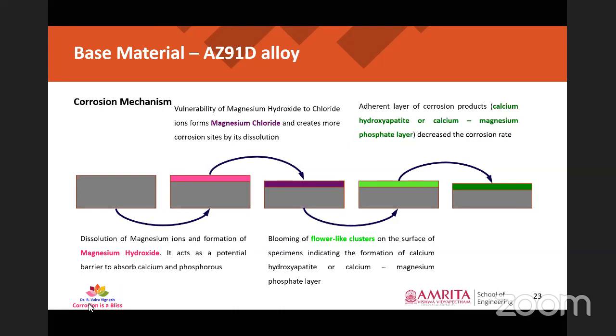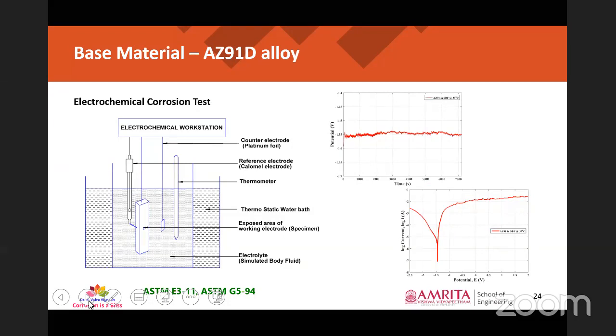But the corrosion rate of this specific alloy is around 4.37 mm per year, which is not recommended. So that is why we have to go for a process that will engineer the corrosion rate of this material specifically. And we have done an electrochemical corrosion test to assess the corrosion rate and corrosion potential of this material. This I'll be detailing with respect to the AZ91D silica based composite. In this process, we have taken the base material and immersed it in an SBF solution, which is Dulbecco's phosphate buffered solution, to mimic the human body environment.